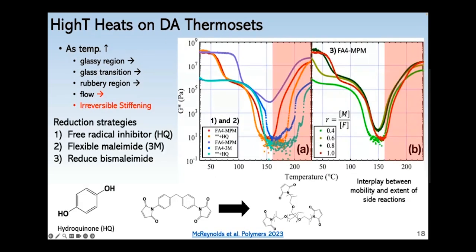And now I'll be moving on to our results to study the maleimide self-reaction. In this slide, I plotted up again G star against temperature. At high temperatures, the DA polymers are expectedly initially flowy, but after some time and at high enough temperatures, it became really apparent to us that some irreversible stiffening has started to occur with these samples. And so we tried various strategies to minimize the maleimide self-reaction. In the first strategy, we introduced a free radical inhibitor, like this hydroquinone molecule.